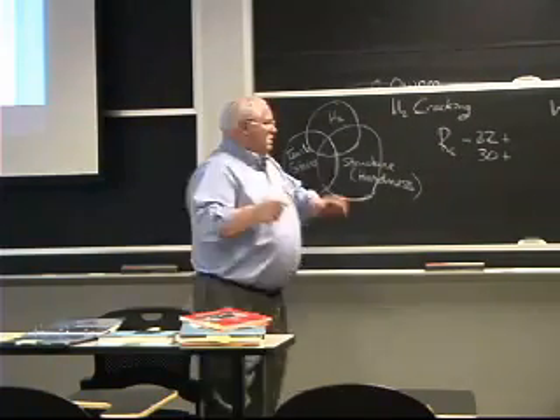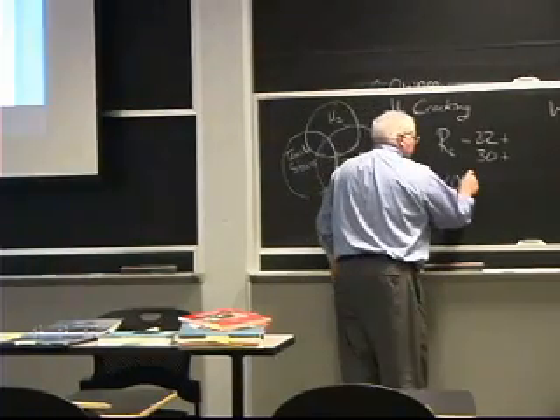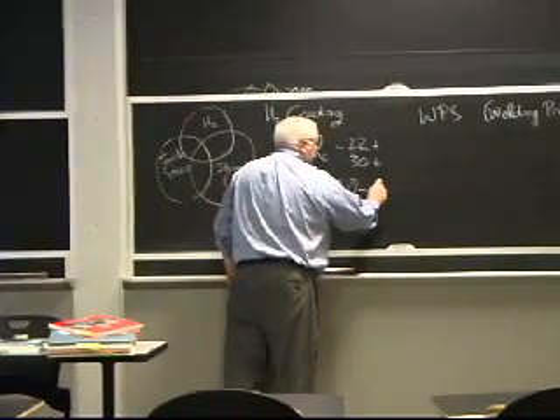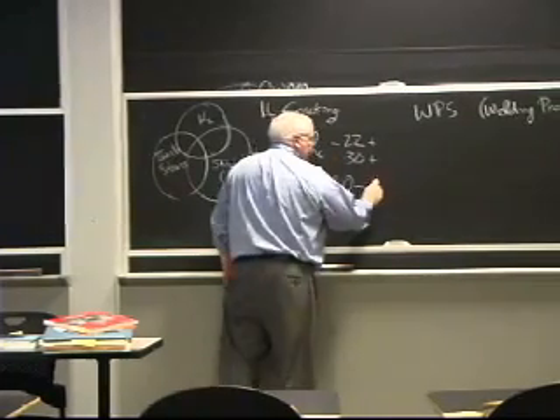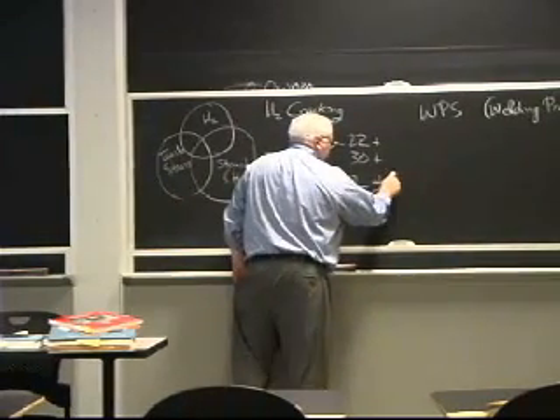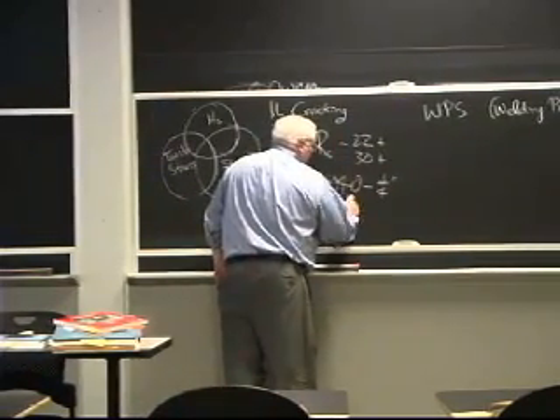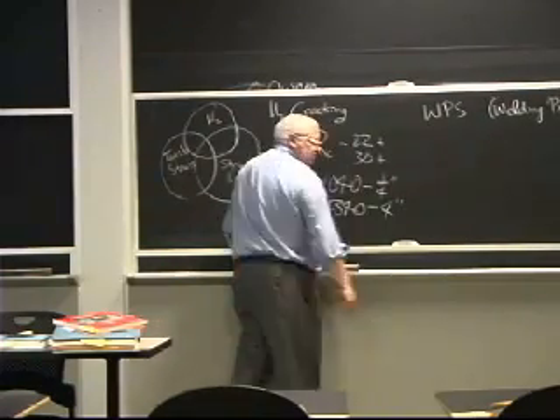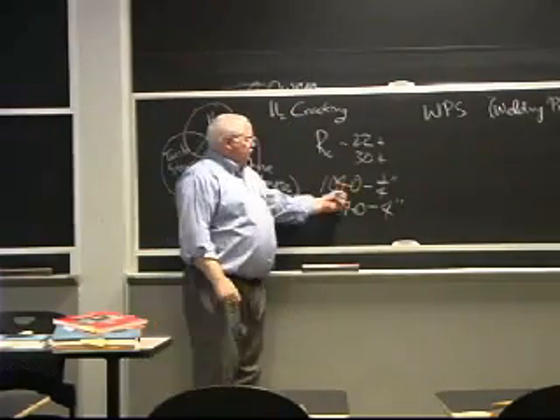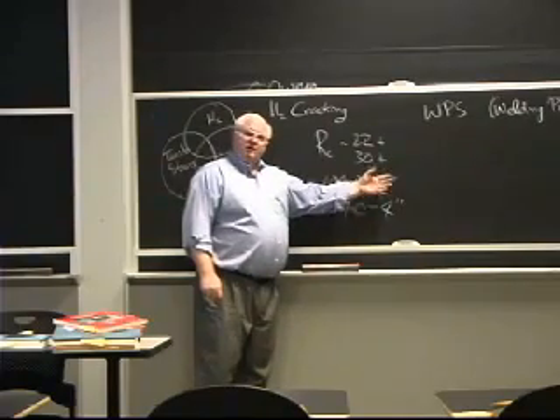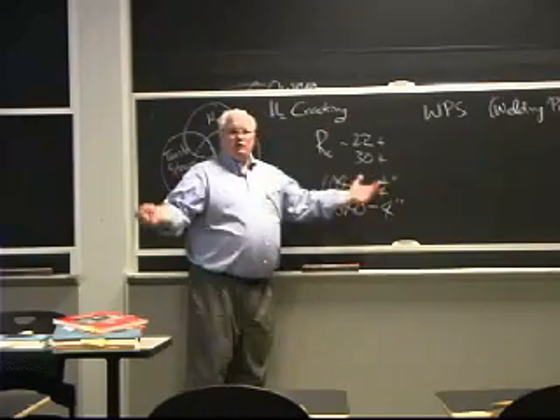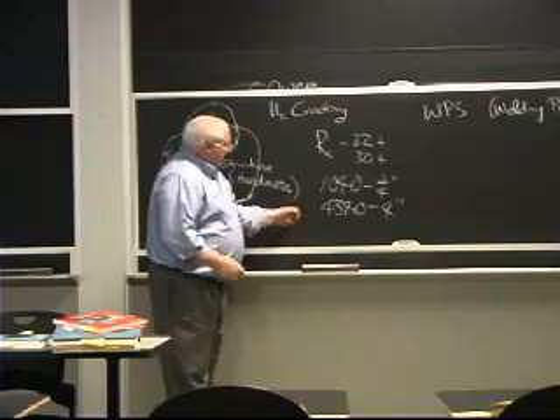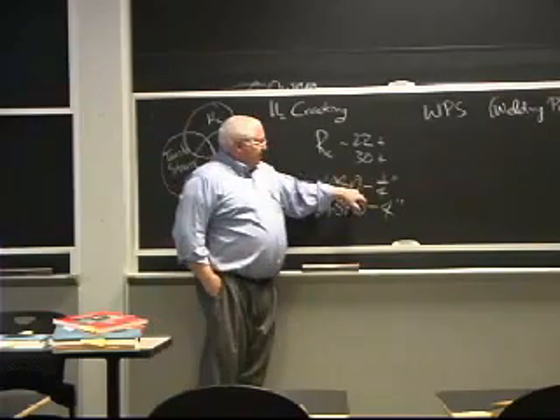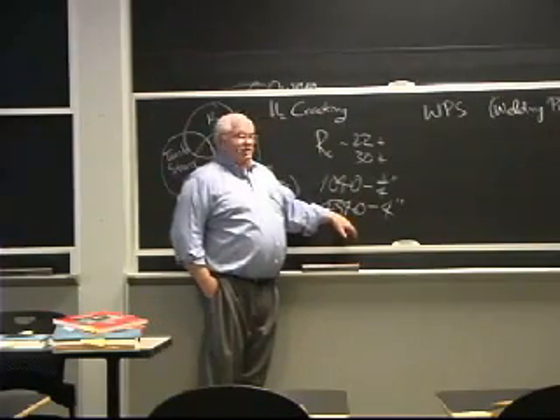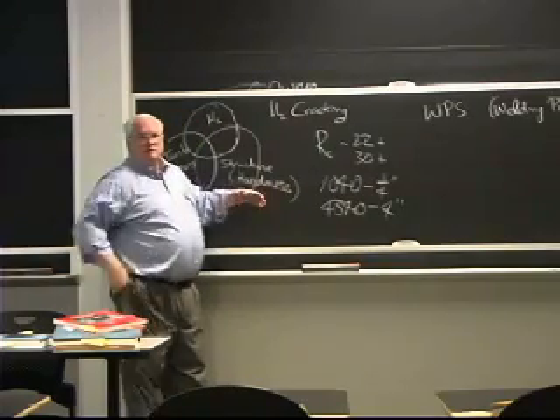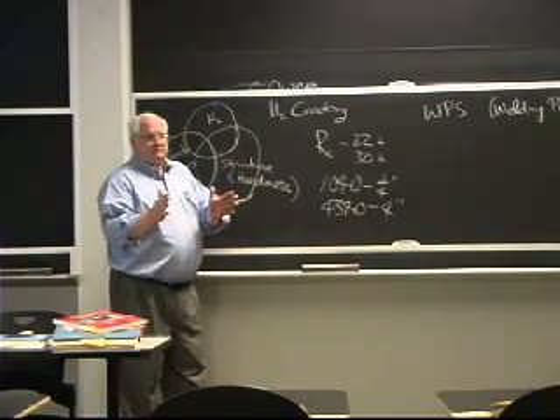For example, with a 1040 steel, just a simple plain carbon steel, I probably can't get uniform hardness through the thickness over more than about 1/4 of an inch. But a 4340, I can get it over 4 inches. Okay? And there's a 4140 in between, it has less alloying element, I can probably get it up to 1 inch. And that's one of the reasons we have so many steels around, because they have different amounts of hardenability. These all have 0.4% carbon, and so they will come up with roughly equivalent hardness, but in different section thicknesses.